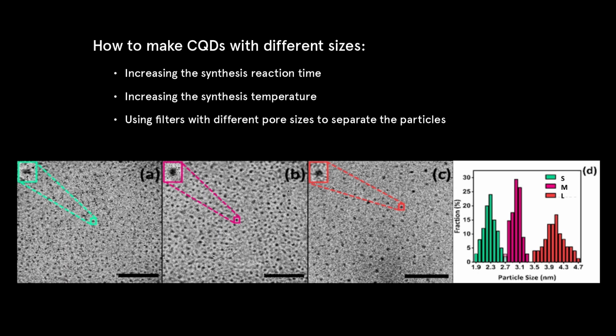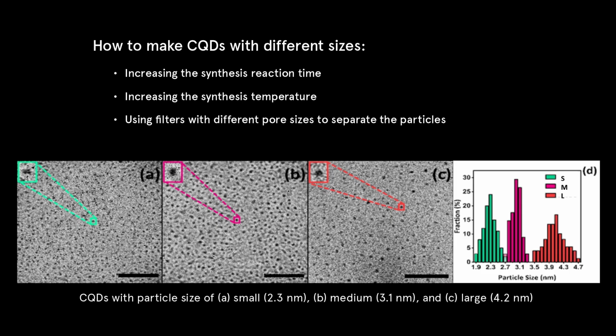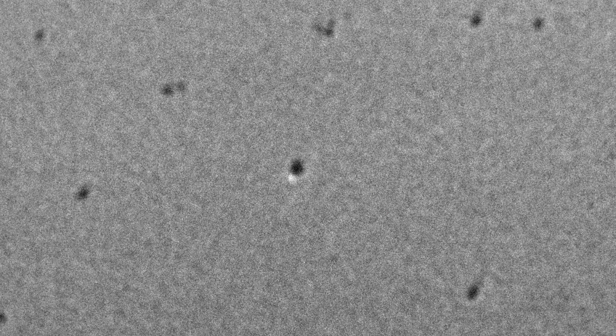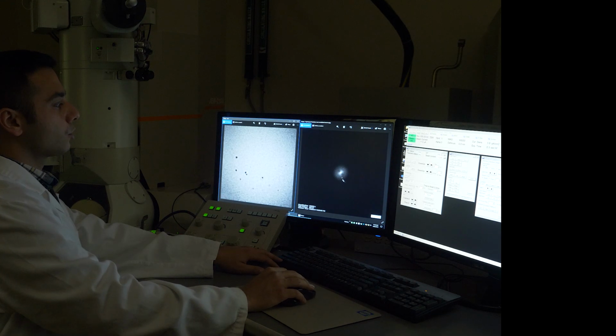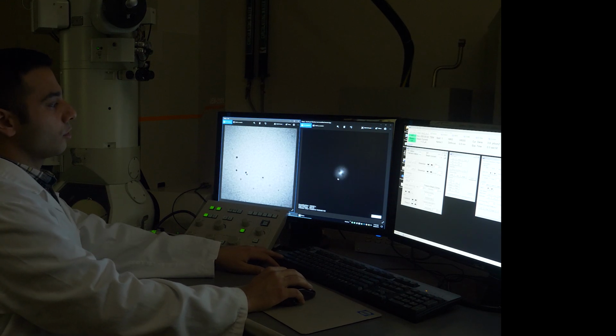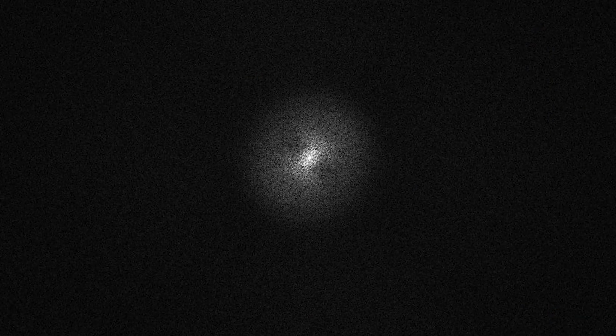Or here, I have used 3 filters with different sizes to separate the synthesized carbon quantum dots based on the particle size. You can see when I use a filter with small pore sizes, I could achieve particles with the average size of 2.3 nanometers. And then by using a filter with larger pore sizes, I could obtain carbon quantum dots with particle size of 4.2 nanometer. Also, the fast Fourier transform or FFT show no diffraction, which also shows that these dots are non-crystalline in their structure.